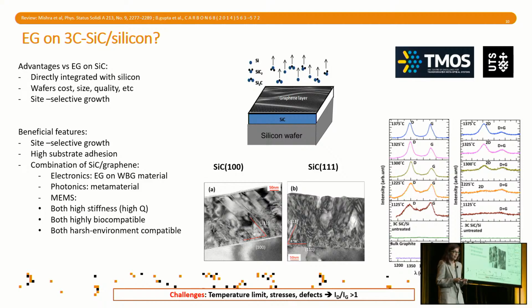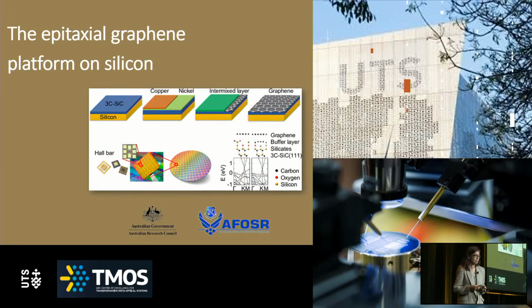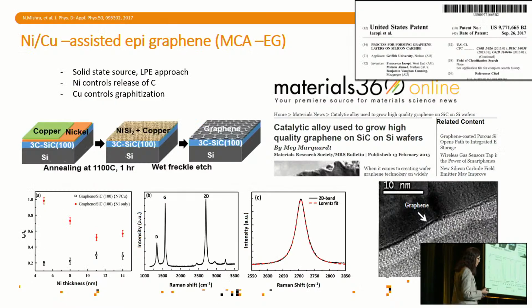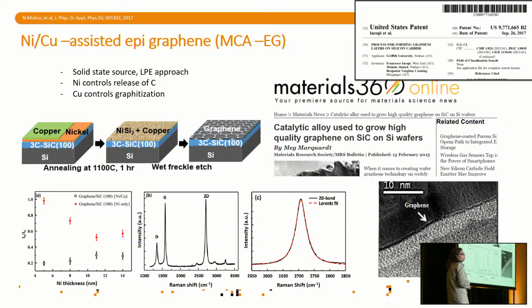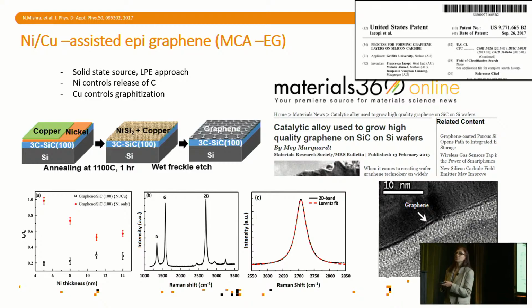So what did we decide to do? This is where we came in. From my previous experience with nanowires, we were working a lot with catalysts. Catalysts always help, as you know. However, here we had to use a little bit of a more complicated trick than just using catalysts by themselves. Nickel in contact with silicon carbide forms silicides. So it helps basically to lower the temperature at which you can release the carbon and use it for the graphitization of the system.